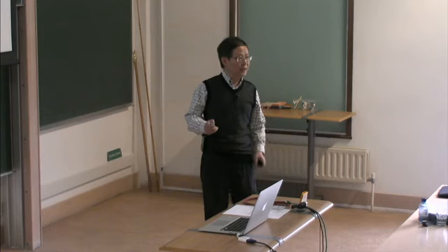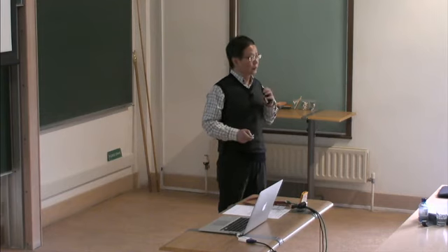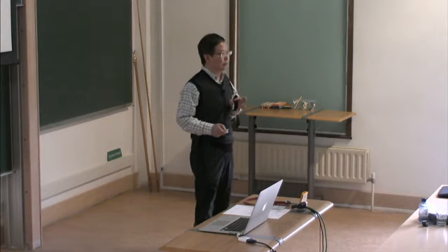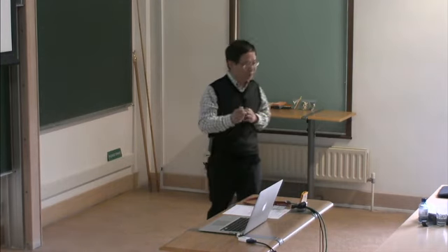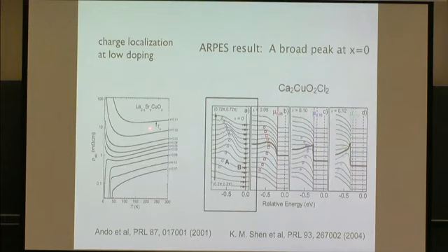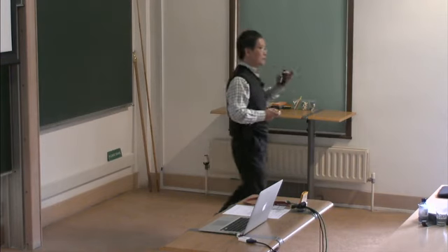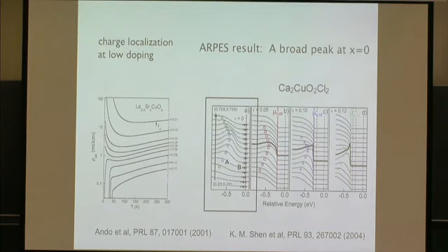Experimentally, you find that when you dope this system, from that cartoon picture I just gave you, you would have some mobile charge. But experimentally, this doped charge becomes metallic at high temperature, but at low temperature, there's a resistivity divergence. In other words, this charge is also localized until some critical doping where it becomes superconducting, so the resistivity drops to 0. And in this regime, you don't see a very sharp quasi-particle peak. You see very broad features.